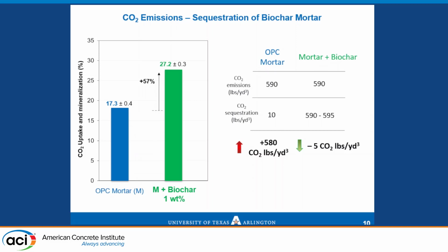So in this slide, the right part, you see the CO2 emission sequestration, the numbers after 28 days of carbonation, and from the calculations you will see that the biochar mortar exhibits a slightly higher CO2 sequestration capacity, which leads to a total removal of CO2 of about 5 pounds per cubic yard.